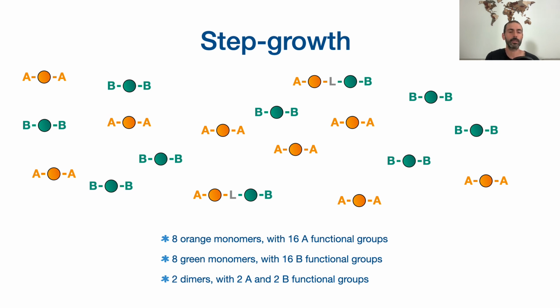The reaction occurs in small steps, meaning many monomers first need to react with one another and form a significant number of dimers before these will react with a monomer and form a trimer, so polymer chains again with 3 repeating units. And to see a tetramer, so with 4 repeating units, well, either 2 dimers combine and form a tetramer, or a trimer reacts with a monomer, since, well, 2 plus 2 or 3 plus 1 both give 4.